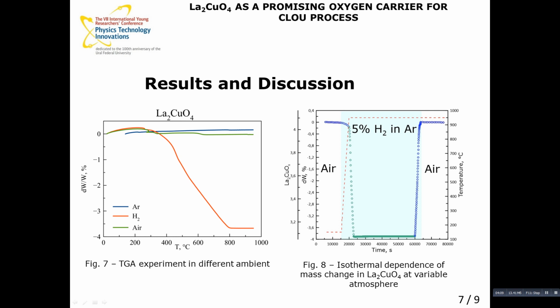Thermogravimetric experiments show lanthanum cuprate doesn't possess any significant changes in oxygen content on heating in air or argon, as depicted in Figure 7. But in 5% hydrogen in argon, lanthanum cuprate loses up to 3.9 weight% at 950 degrees, which could be considered a good oxygen capacity for CLOU. The single cycle presented in Figure 8 shows no significant degradation, with oxygen content deviating between 4.1 and 3.15.